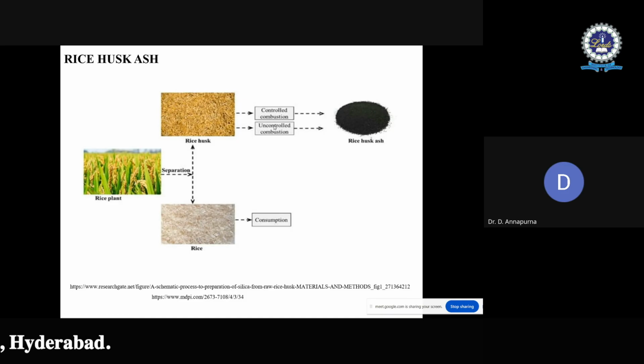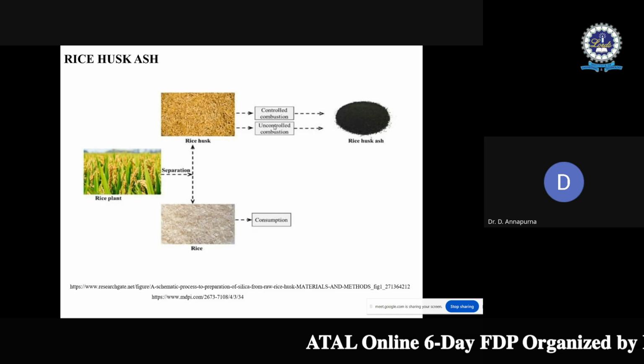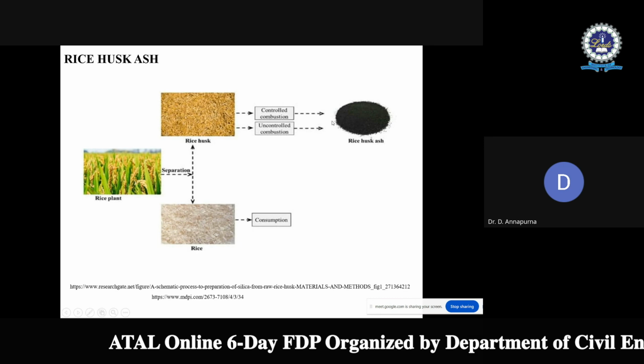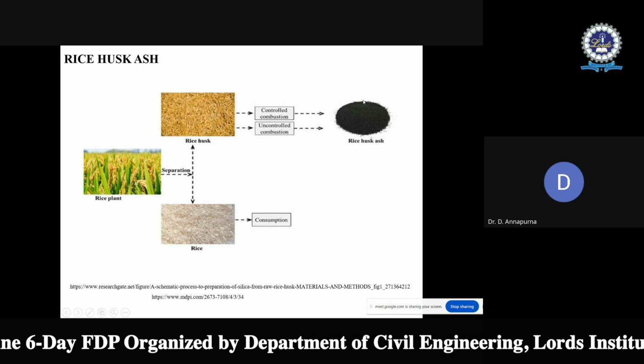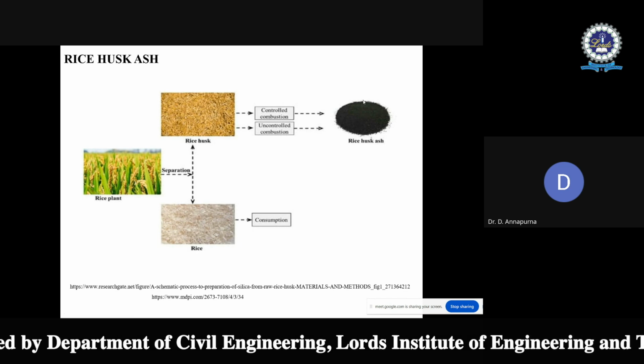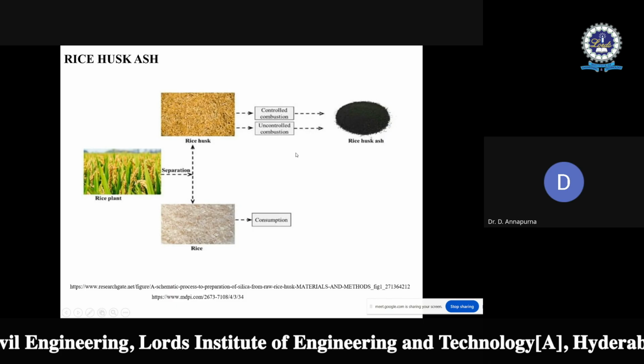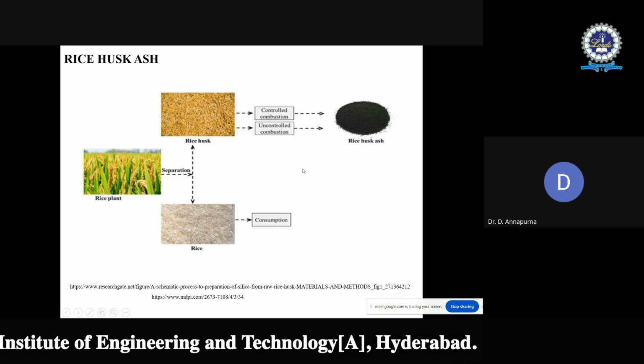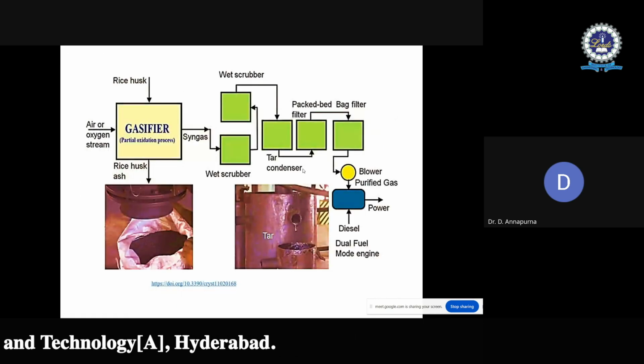So it will be dried, and this rice husk will be burned at a temperature of 600 to 800 degrees Celsius. Then the ash will be cooled and ground again to get the fine powdered form of this ash, which is called rice husk ash. It is also rich in silica content and the fineness will be very high.